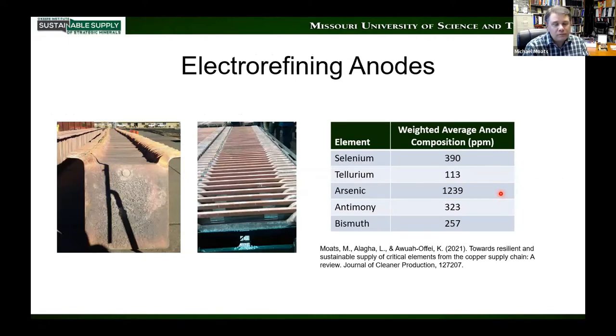Finally, we're at the anode. So we've now gone through the smelting process. We've gone from a concentrate, which has maybe 25 to 30 weight percent copper in it, through smelting, which gets us up to a matte of 50 to 70% copper, and then finally a crude copper of about 98, 99%. And we get to anodes that are around 99%. So there's a line of anodes. I think I took this down in Mexico at the Nacozari refinery. And we put those anodes into a bath of copper sulfate and sulfuric acid, and we electrorefine them.